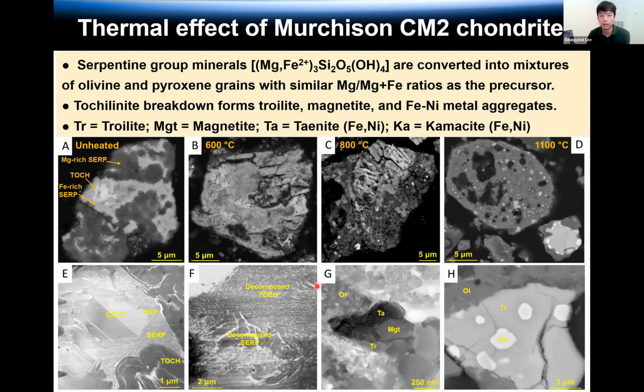But at higher temperature, these minerals recrystallize. So decomposed serpentine transforms to nano-sized olivine grains. And the tochilinite area, because it has sulfur, becomes troilite, and also some iron oxide, magnetite, also iron metal complex. At higher temperature it is much clearer, showing the olivine is a secondary olivine growth, and this is troilite. Also, Ka forms a kamacite iron metal complex. This area originated from the tochilinite area, and this area originated from the serpentine area.